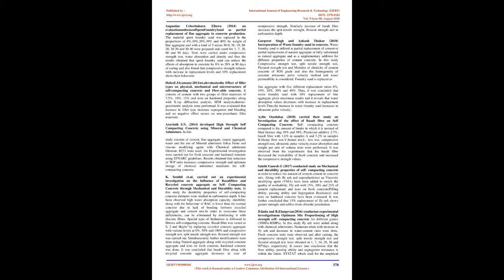From this study it was found that the increase in strength attributes to the bonding property of cement paste, and thus the compressive strength increases between 200°C and 300°C. Augustine Uchechukwu Elinwa, 2014, an evaluation of spent foundry sand as partial replacement of fine aggregate in concrete production.